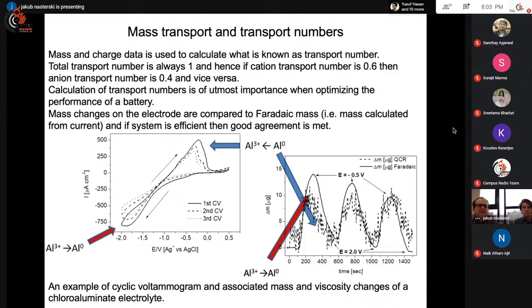Now, Faradaic mass is a mass that would be exchanged if all the electrochemical reactions taking place in your battery would be 100% efficient. So essentially, if your battery is efficient and you start charging it, all of the current would be used to contribute to mass changes at your electrode. Now, that doesn't really happen in real life, but you can see here some electrochemical reaction where on the left you have pure electrochemistry, so essentially oxidation and reduction. And on the right, you can see the associated mass changes and viscosity and mass changes, and this mass change is compared to the Faradaic signal.